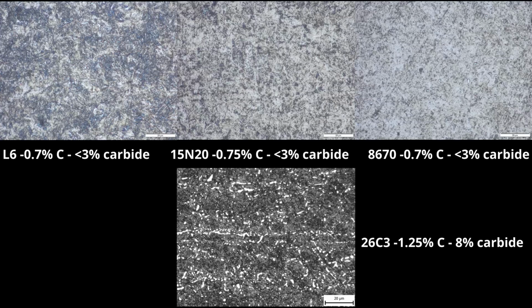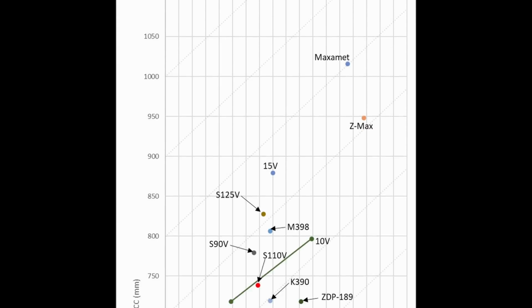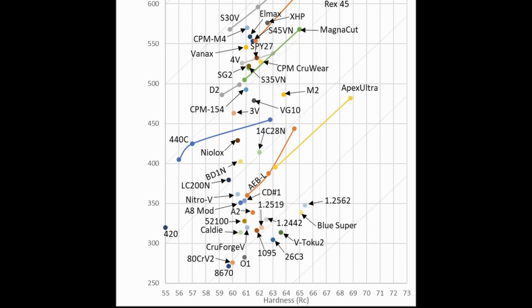So you can have a steel which is only 50 Rockwell with lots of hard carbides that is more wear resistant than a steel which is 66 Rockwell which has no carbide. That's the effect that carbides can have. So these steels with almost no carbide in them are quite low when it comes to wear resistance and slicing edge retention. So this is a chart of my Catra slicing edge retention testing, where you can see that the very lowest steel on this chart is in fact 8670. It was only about 60 Rockwell, and it has very little carbide.